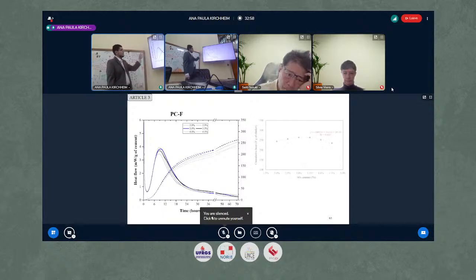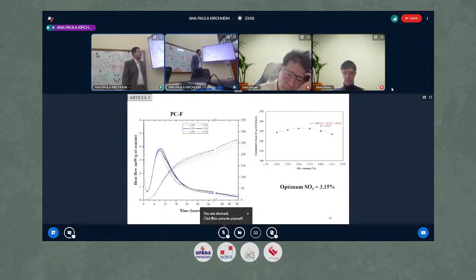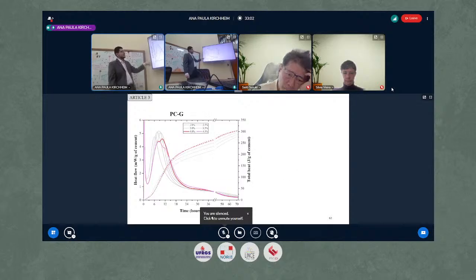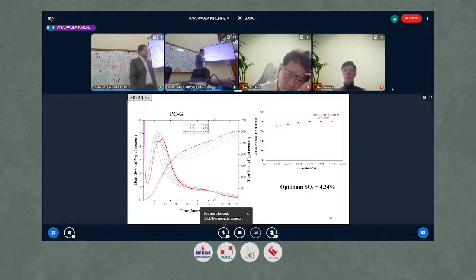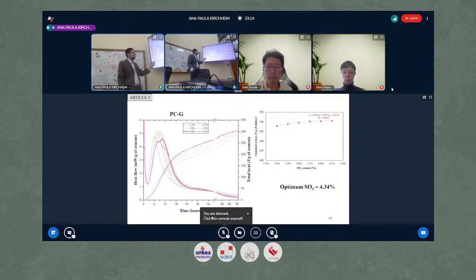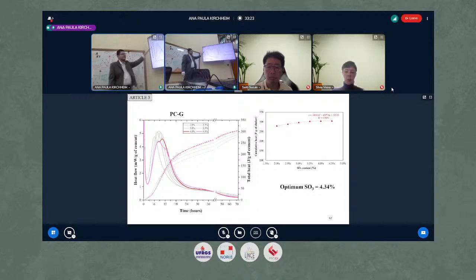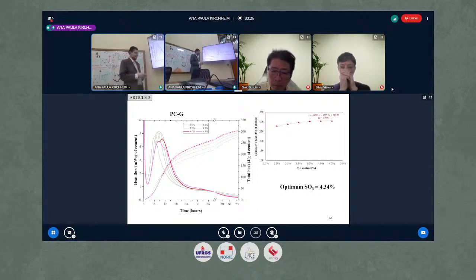PCF again 3.15%, and PCG a very high sulfate number, 4.34%. It's important to highlight here that this optimum is more a range than a point itself. With this method, we get an optimum content, but it's more a range, so here between 4 and 4.5, than a point itself.